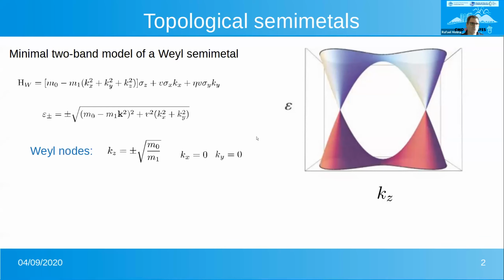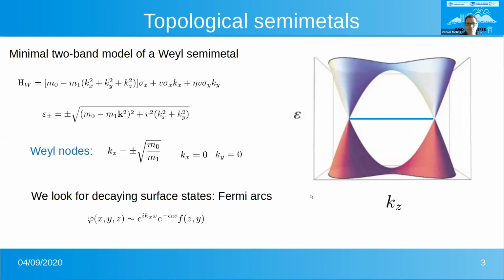And of course, you can solve this model and you find this band structure. If M0 and M1 have the same sign, you have this mass inversion, band inversion, and these two band crossings, the Weyl nodes, at this position here. And we can look for decaying surface states, and those will be the famous Fermi arcs that will be living in just a finite domain in momentum space.